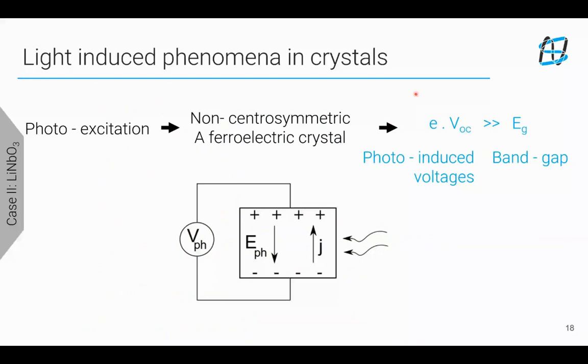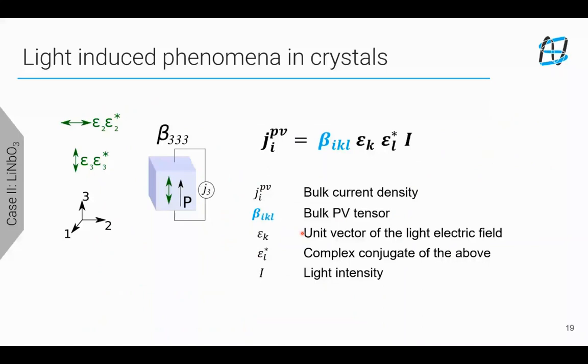Let's not get too much into it, but if you have an incident light, and light also has polarization, then in some specific polarization of light, you get a current charge density. And this is tensorially dependent. The factor which determines the proportionality between the charge density and the intensity is the beta here, which is the bulk photovoltaic tensor. And it is a tensor because of its symmetry.